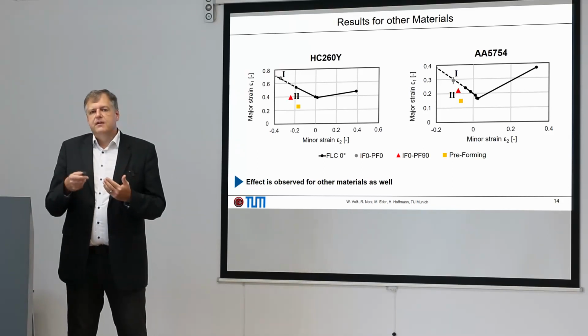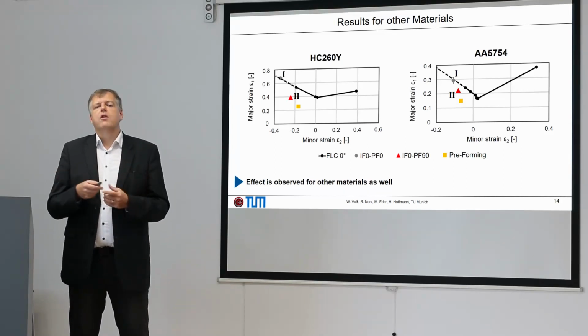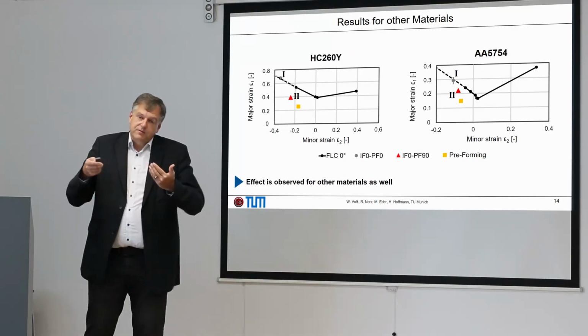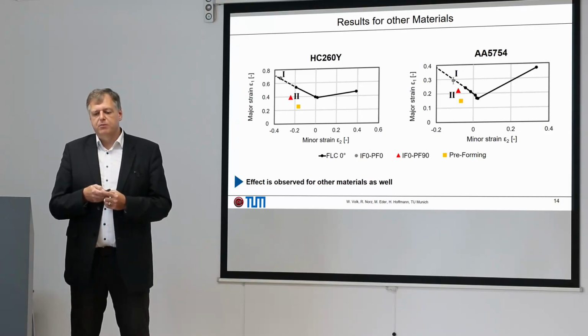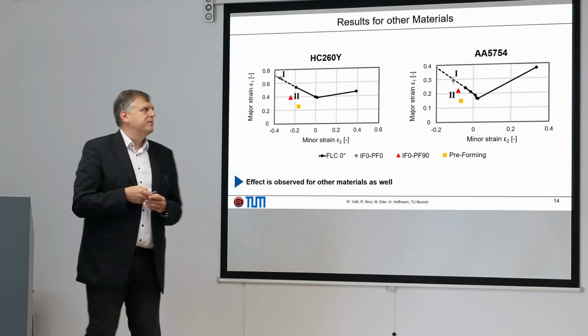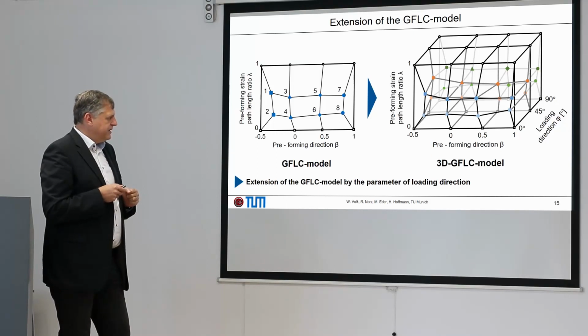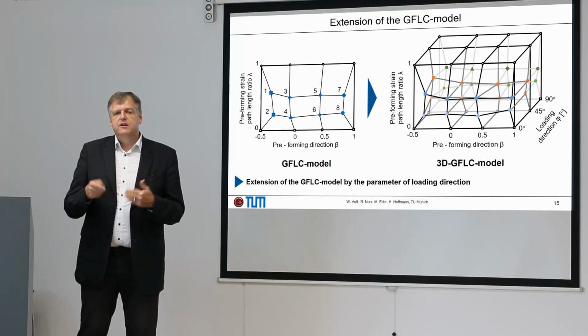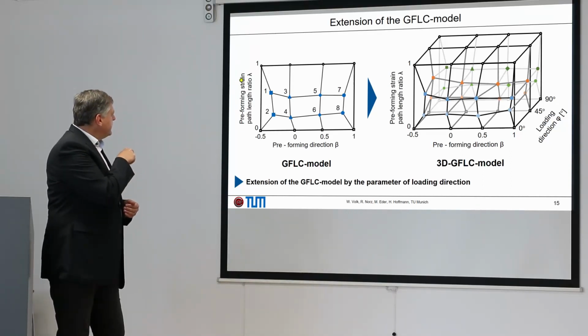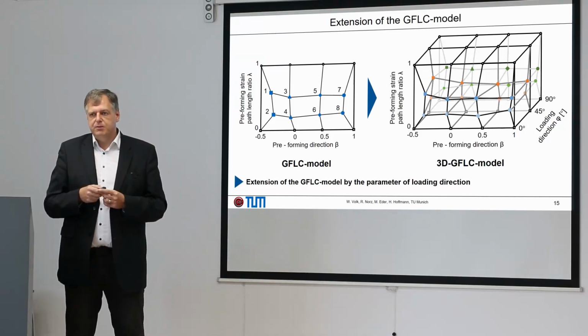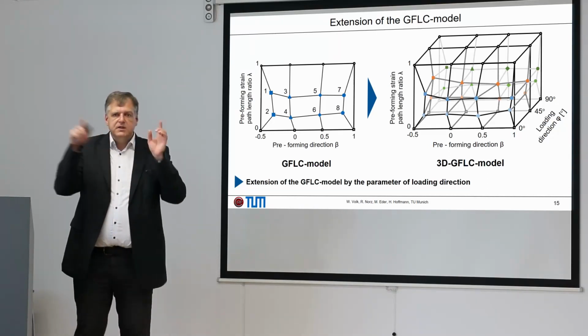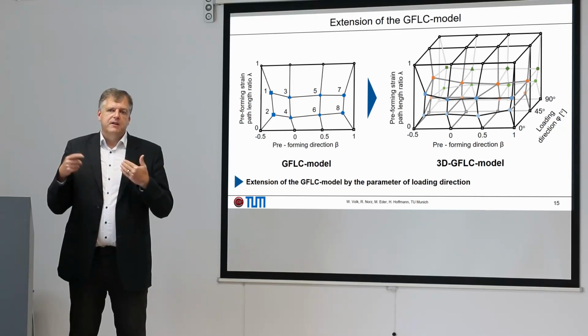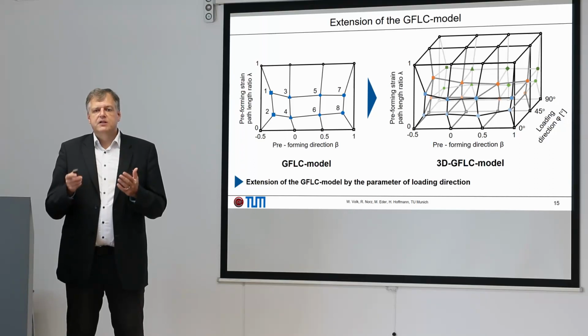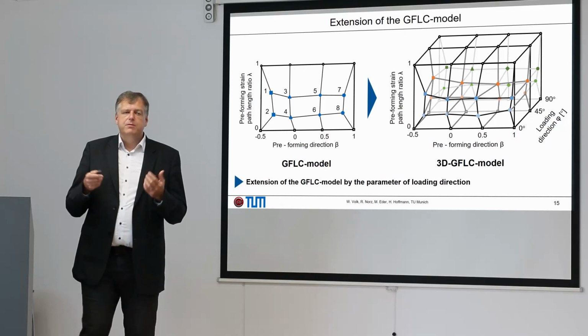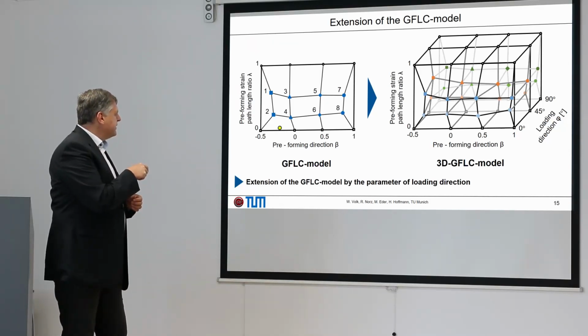And we tried in this paper to start with a well-known way of phenomenological description. Of course, we promoted the GFLC, which is a pure phenomenological model, and tried to extend this by taking these experiments into account. What is the idea of the GFLC, just to summarize? The idea is you have to have a suitable amount of experiments. Here you see in the preforming strain length and the preforming direction that these are experiments which you can use with the Nakajima test. And on all these points, we do post-forming steps, for example, for experiments, where we have a remaining FLC. And the basic idea of the GFLC is just to interpolate this given information to any possible preforming combination of preforming length and preforming direction.